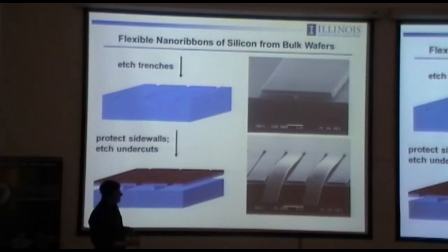If you do that, then you end up with a form of silicon that's really floppy and flexible just by virtue of that cubic scaling of bending rigidity with thickness, number one. And then number two is for any material, the peak bending strains go down linearly with thickness. So not only the degree of bendability, but the bending stiffness are dramatically impacted by just making the silicon thin. So that works pretty well.